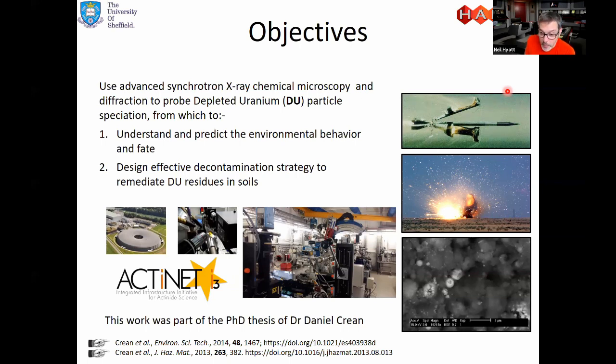It's this property, combined with the high density and hardness, that makes uranium the material of choice for this application. However, pyrophoric oxidation of the penetrator produces uranium oxide particulates, and the conversion of penetrator to particulates is typically 15 to 35% of the initial mass, and maybe up to 75% of the initial mass. The potential long-term health risk is from resuspension and inhalation of these particles, which have a small characteristic size. There may be a requirement to remediate at some sites with high particulate and high contamination levels, such as at firing ranges.